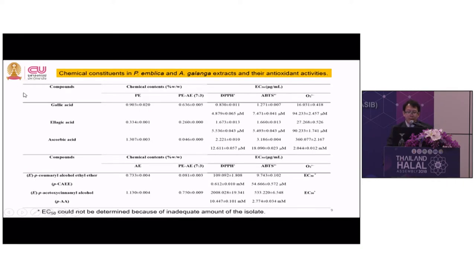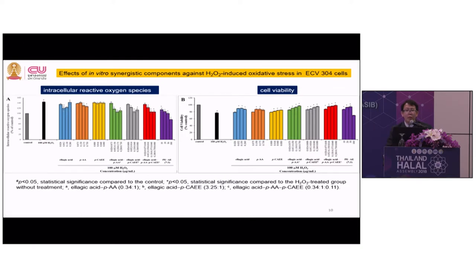And this is the amount of the chemical compounds in the extract and their antioxidant activities. I also investigated the two-compound synergism by mixing one compound from emblica and one compound from galanga, and the result shows that ellagic acid when paired with para-acetoxy cinnamyl alcohol, and ellagic acid when paired with para-coumaryl alcohol ethyl ether, can have a synergism effect by decreasing intracellular reactive oxygen species and increasing cell viability.